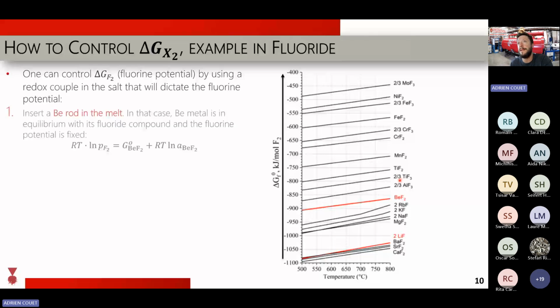So how do you control that? Well, one way to control the partial pressure of fluorine or chlorine in your salt, for the fluorine case, is to use, for instance, a beryllium rod. You see that beryllium fluoride is extremely stable. So beryllium is going to be in equilibrium with beryllium fluoride, and you're going to bring the redox potential of your salt very low. So it's basically an insoluble-soluble type of redox buffer.